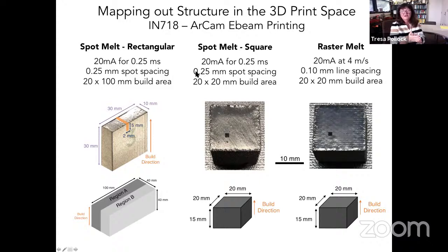Okay, so let's talk about 3D printing at the melt pool scale. And what I want to show are 3 different experiments and the sort of information that we can get by looking at the structure at the scale of the melt pool. And so what these experiments are is electron beam printing of the nickel alloy Inconel 718. And what we've done is basically printed to steady state. And then on the very last layer, put different sorts of conditions so that we can understand the relationship of the printing conditions to the structure that develops.